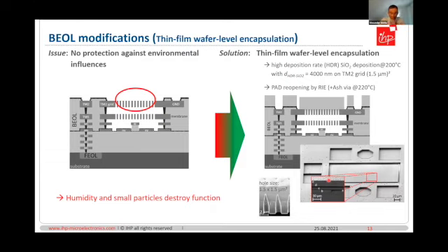Finally, there's still a lack of MEMS protection, so humidity and particles can destroy the MEMS function. In order to provide a feasible protection, the thin film wafer level encapsulation is done by a high deposition rate silicon oxide deposition at 200 degrees C, with a target height of 4000 nanometer on top of the top metal grid. Afterwards, the pad reopening by RIE and the subsequent resist removal by an ash process at 220 degrees C has to be done. So you see this right here.